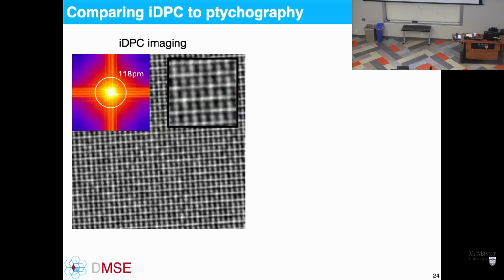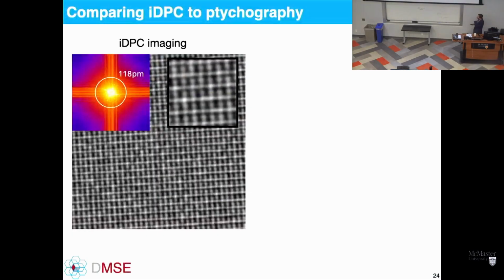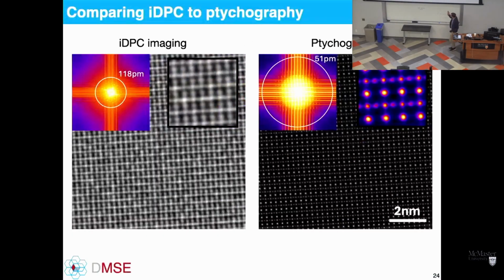And just to compare here, coming back to this lead magnesium niobate, lead titanate sample, with iDPC imaging, you can see oxygen. But when you go to ptychography, I think I just muted the thing. Yeah. When you go to ptychography, that's the result. Now you can really see where oxygen is at. You can see where the cations are at. Now you can really measure polarization, and not just polarization in two dimensions, but polarization in three dimensions, as I'll show.